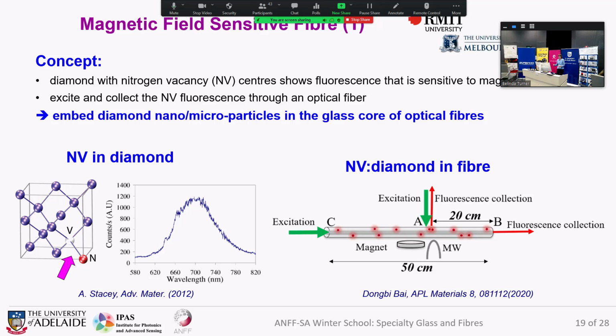You have the green light for excitation, and then we collect the red fluorescence on the other side of the fiber. So you can imagine, to do this we need to get the diamond nano or microparticles into the glass core of the optical fibers.